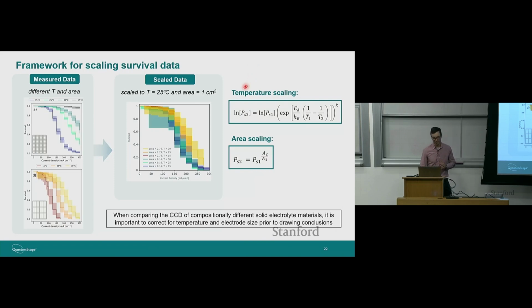So first of all, the temperature scaling happens to be an Arrhenius scaling factor. This is because of the mechanical properties of lithium. Lithium melts at 180 degrees C, so even at room temperature, it's above its homologous melting point. So its mechanical properties, its flow, its creep, are depending on temperature. So that is why there's an Arrhenius behavior with temperature. But this scaling law allows you to then understand how your solid-state electrolyte would behave across temperature.